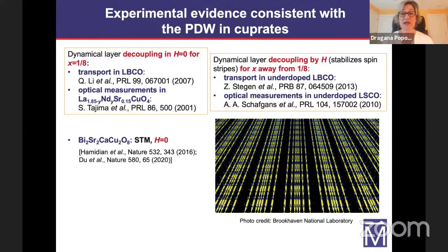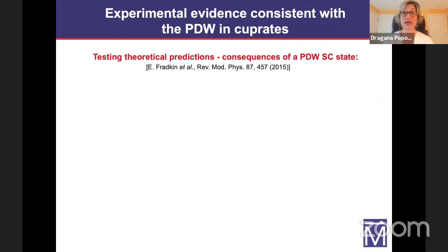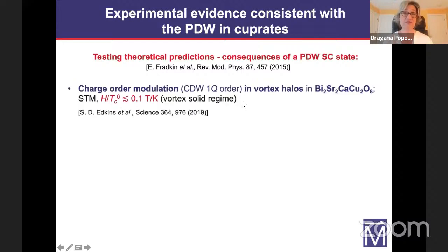Even though all of these data are consistent with the presence of a paired density wave, it has been argued that other interpretations might be possible. So in more recent years, people have also focused on actually trying to test and confirm theoretical predictions, which are, for example, listed in this nice review paper here. One such prediction was that in the presence of both uniform and paired density wave orders, it should be possible to detect another component of the charge order modulation.